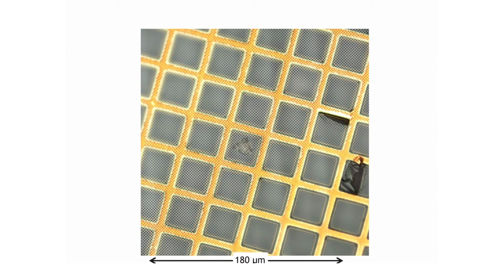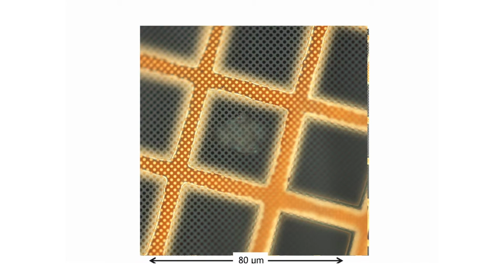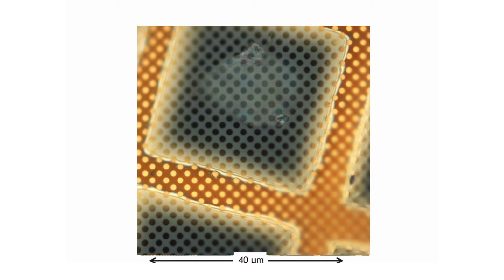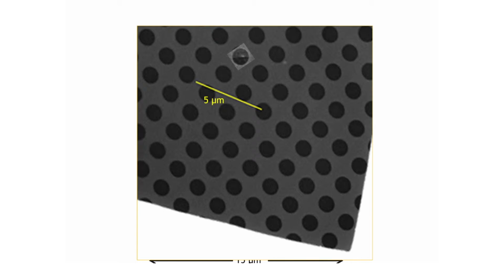Here, I show a small, transparent graphene flake, suspended on a holey carbon grid, which in turn is suspended on a larger gold grid. And you can see, if I enlarge it, there are obviously the holes in that film, which are important to let the electrons go through. So when I reach the end of the magnification that I can get in an optical microscope, I have to put this sample in an electron microscope and I can further enlarge it. There is the edge of the graphene. And then we see something very, very amazing.